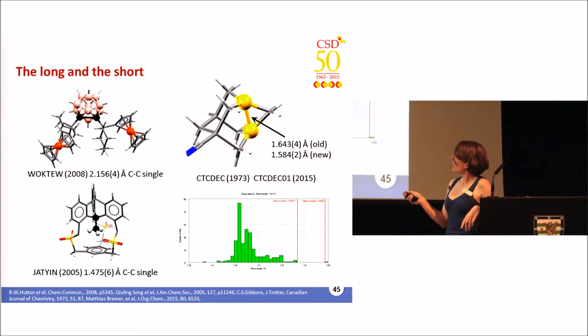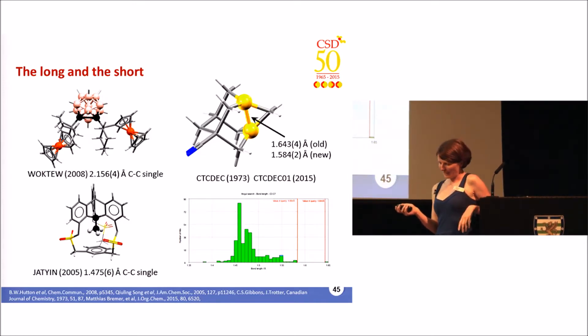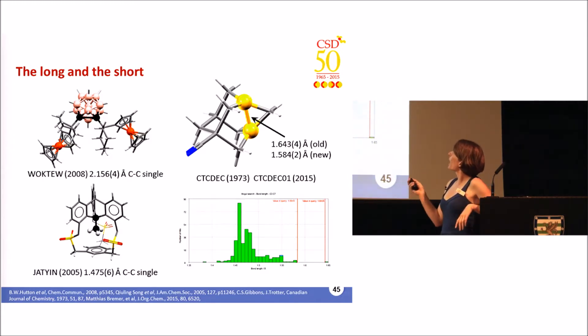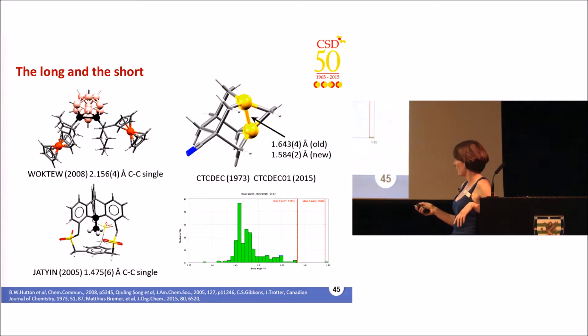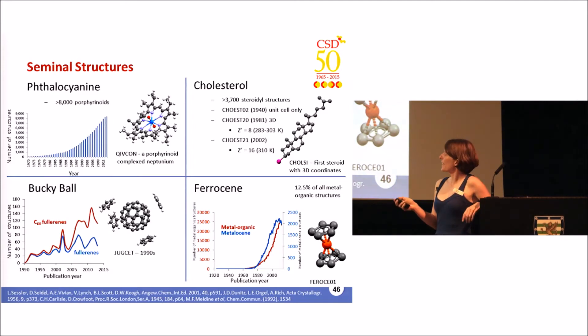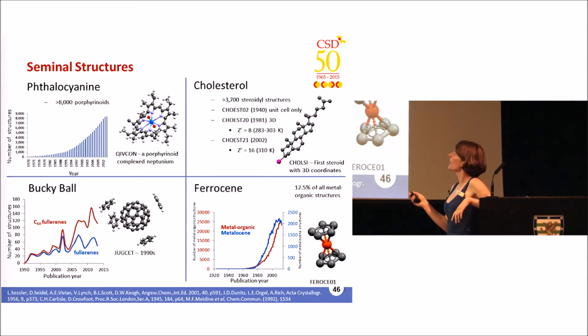I quite like looking at extraordinary and out-of-the-ordinary structures. This structure has a really long carbon-carbon single bond, whereas this one has a really short one. You have to be careful if your structure isn't normal — this one was done in 1973 and was just redetermined this year because they didn't know whether that bond length was believable. When they looked at the distribution of bond lengths in the CSD using Mogul, the original structure was well outside the normal distribution, and the new structure has a slightly shorter but still quite long bond that just fits at the edge. There are also lots of seminal structures in the CSD — you can see the rise of porphyrins, when cholesterol was first determined, and the rise of ferrocene, which now appears in over 10% of metal-organic structures.